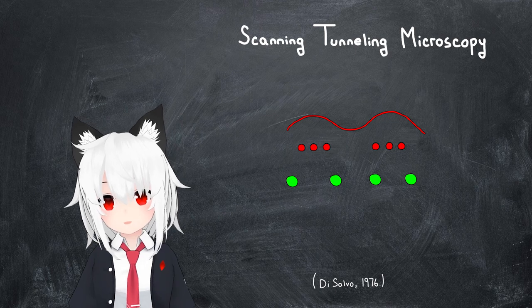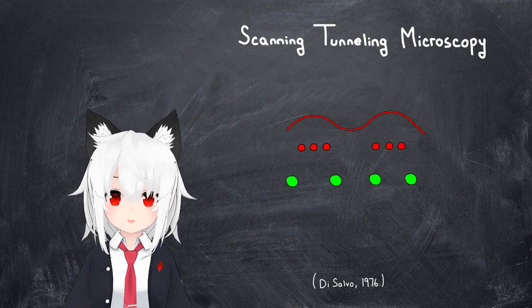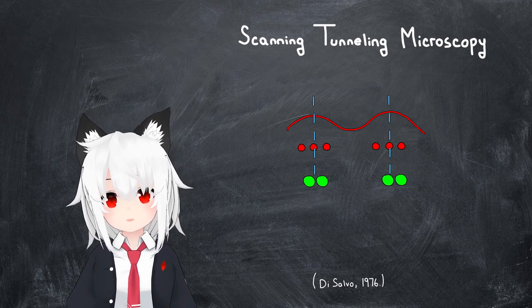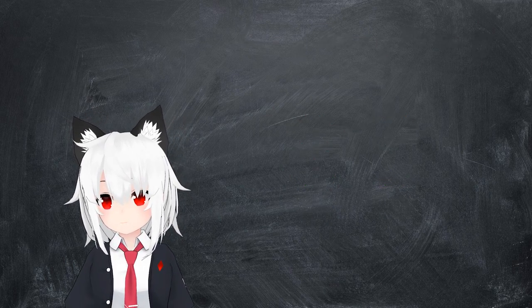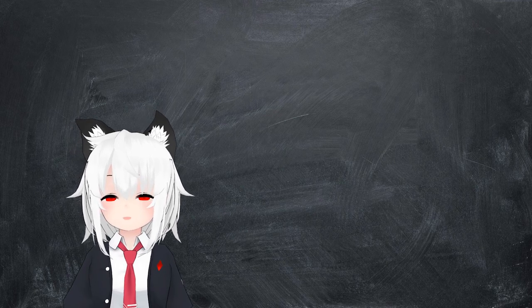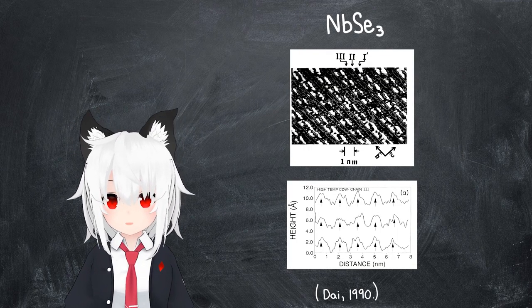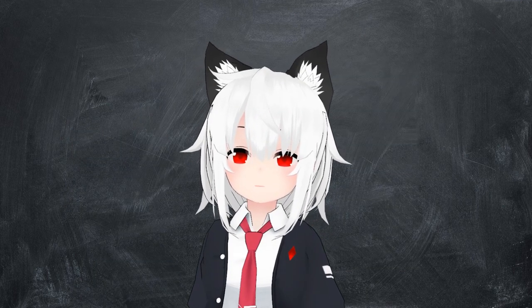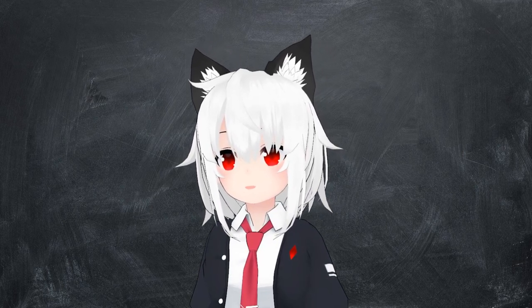This provides a fairly straightforward means of directly probing the positions of atoms on a lattice, and in the presence of charge density wave ordering, the positions of these atoms should be expected to shift in accordance with the periodicity of the charge density wave. And what do you know? This is exactly what was observed in the quasi one-dimensional material niobium triselenide. So that's already one hint at the existence of charge density wave ordering in quasi one-dimensional materials.